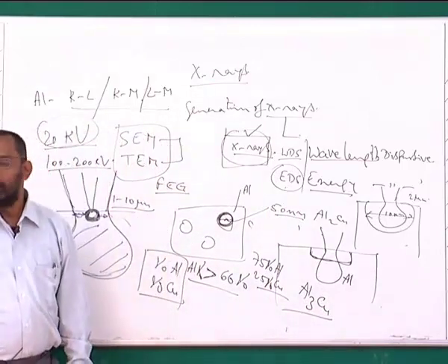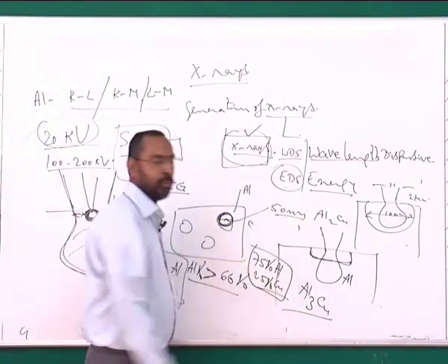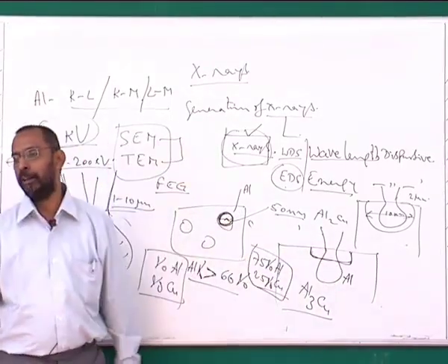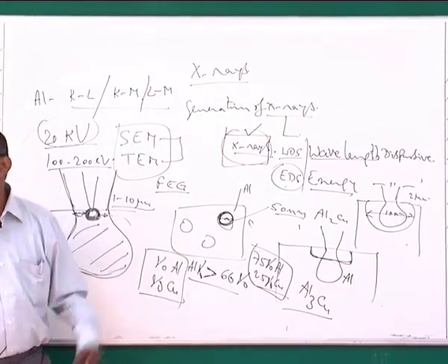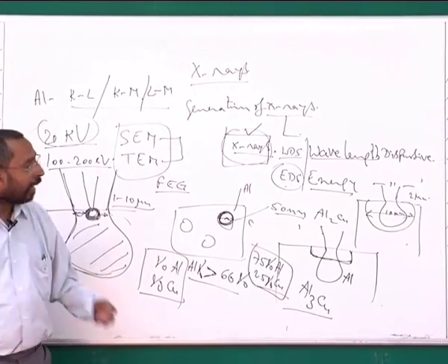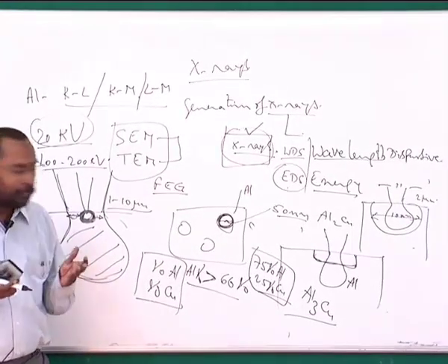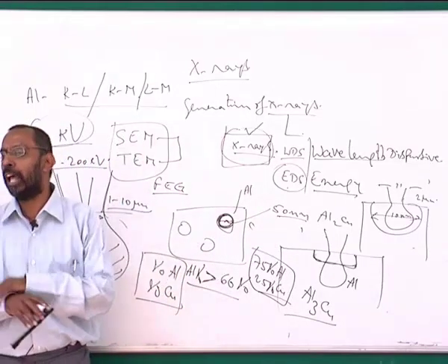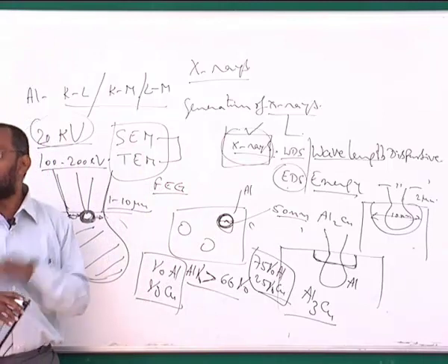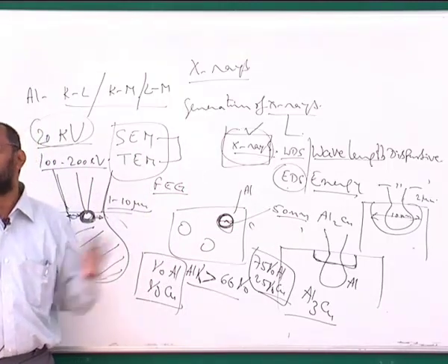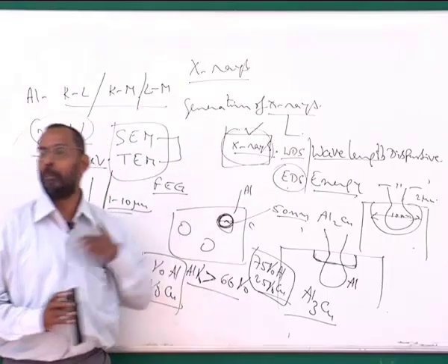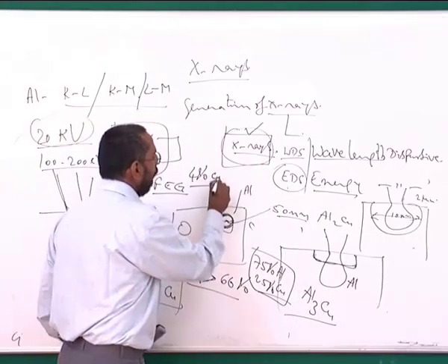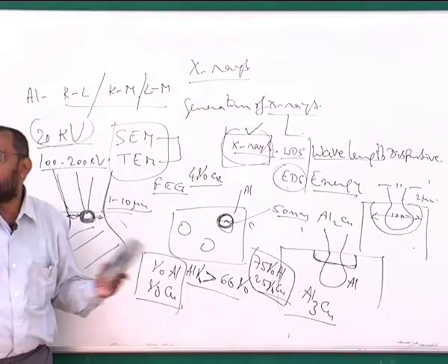particle. So if the quantitative analysis gives me an idea that there is an Al3Cu particle, then I get a confusion. Is it Al3Cu, or is it Al2Cu? That is when you will have a confusion about the nature of the particle. If you have some background information about the alloy, you can go back to the phase diagram and see whether there is an Al3Cu in that particular phase diagram, at the composition of my alloy. If I know my overall composition of alloy, which is 4% copper, I can look at which phases are possible at 4% copper in the phase diagram.